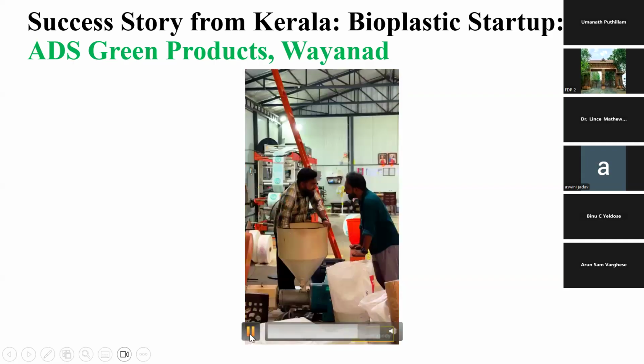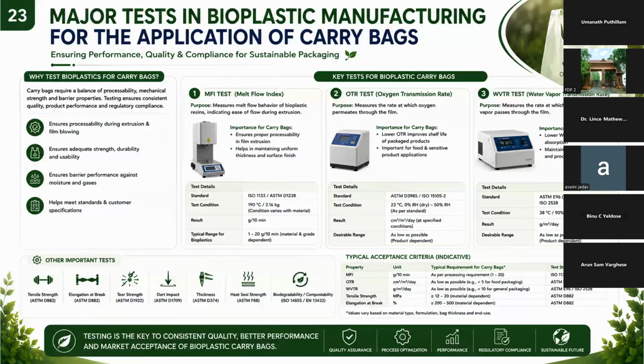And the next slide shows the major tests in bioplastic manufacturing for the application of carry bags. The first test, as we all know, is the tensile test. The standard is ASTM D882, which is the standard for tensile testing of thin films. The next test is MFI, melt flow index. The standard is ASTM D1238.